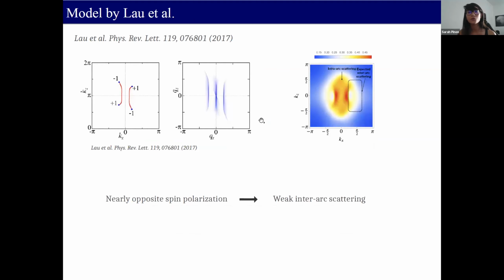We also studied another model, this one proposed in this paper. Here we again have two Fermi arcs, but this time they're a little bit displaced. And this is what they obtained for the QPI pattern. This time they used JDOS, and this is what we obtained. So again, we looked at the spin structure, and we saw this time that the spin polarizations of the Fermi arcs are nearly opposite. And so we expected to have some weak inter-arc scattering, and this is what we observe here.